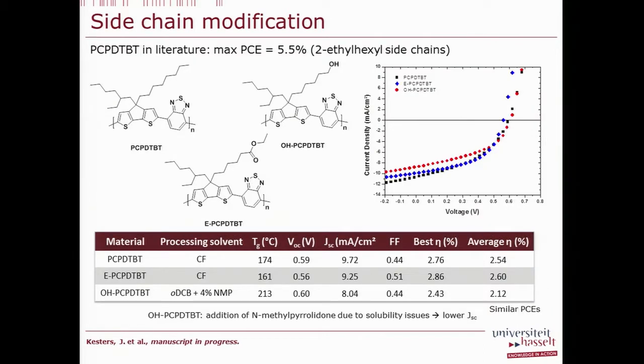And what he's shown there is that if we look to the IV characteristics of these solar cells with these sidechains, a small amount of sidechains, these sidechains didn't alter significantly the IV characteristics, so the solar cell performance was not damaged by that. Also very important, since we're talking about extreme temperature conditions, if you look, for example, at this sidechain modification, the TG was brought up to 213 degrees Celsius. So this is really an extreme high TG material.